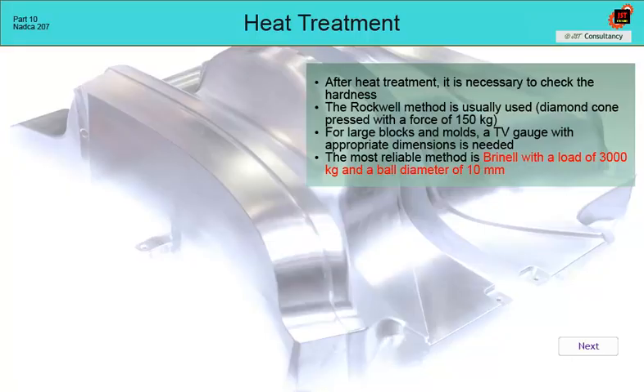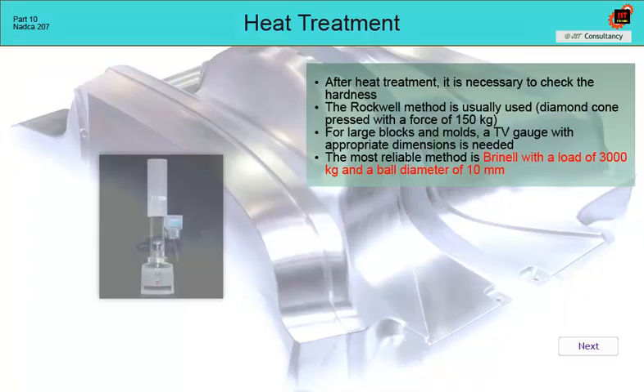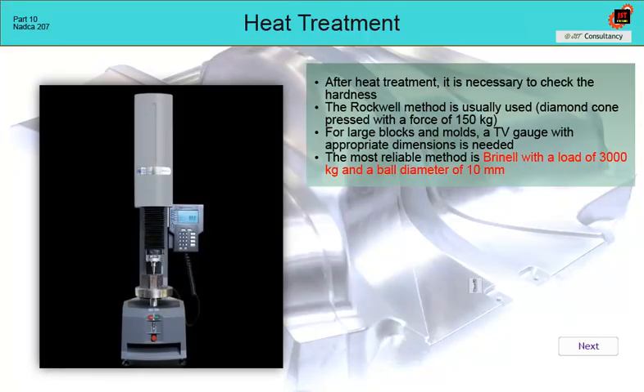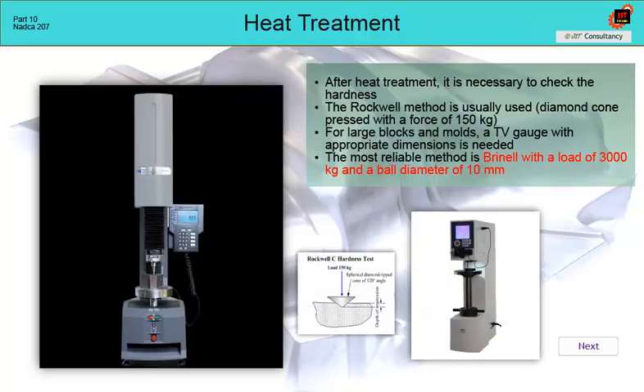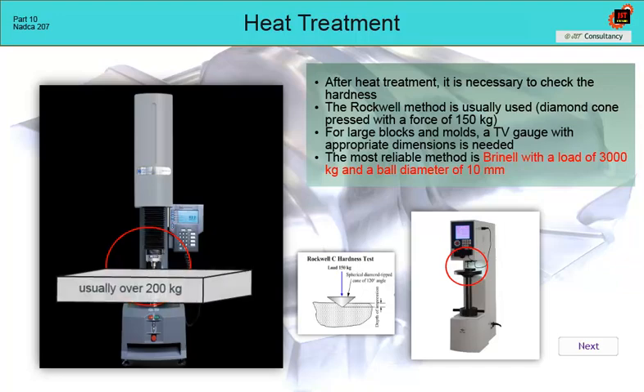After heat treatment, hardness is checked. Usually, the Rockwell method is used, corresponding to the prescribed hardness units on the drawing. However, the problem with classic hardness testers is the size of the table for clamping the part for hardness measurement, as well as the maximum weight of the measured piece.